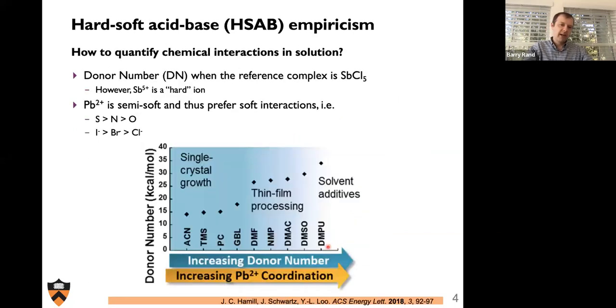And the way that these equilibria are often constructed is on the basis of hard-soft acid-base empiricism, whereby the donor number is used to convey how strongly some solvent will coordinate with some species in solution. The donor number is quantified with a reference complex of antimony pentachloride, which is a hard ion. And I also think this is done in a solvent, maybe it's dichloroethane or something similar to that. And so with this reference complex, it has always been questionable whether this is a perfect analog to what we can expect in lead iodide and solvents such as DMF and DMSO, where lead is a semi-soft ion rather than antimony, which is a hard ion.